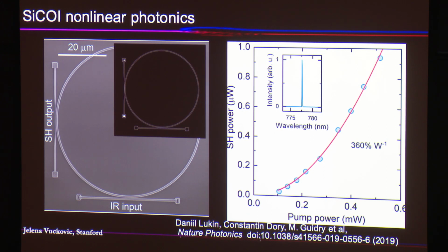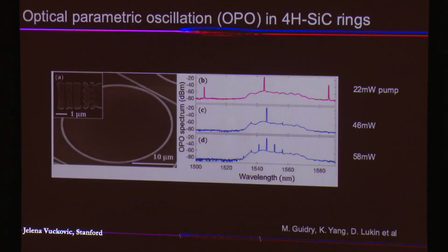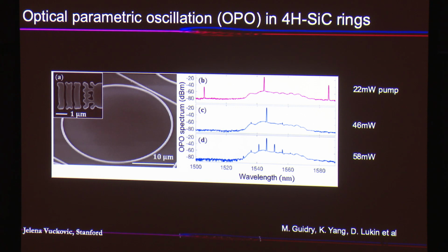I said silicon carbide has second order nonlinearity. So first we did second harmonic generation, and for the first attempt it's pretty good efficiency. It's 360% per watt efficiency, and this is measured relative to the power in the waveguides. So you have your input in one waveguide, your second harmonic output in another waveguide. They're also inverse designed. And then very recently we also demonstrated optical parametric oscillation.